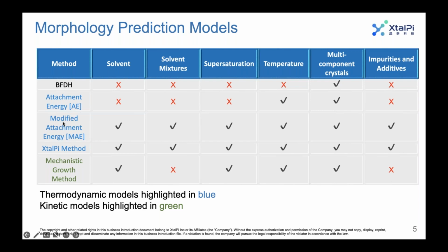Specifically, we use the modified attachment energy model, and we also have an in-house XtalPi method that uses a thermodynamic cycle. The reason we use those methods is because it allows us to take into account a number of different experimental variables, specifically the solvent mixtures, supersaturation, temperature, multi-component crystals, and also the effect of impurities or additives. I'll show you throughout the talk how those different variables can come into play with these predictions.